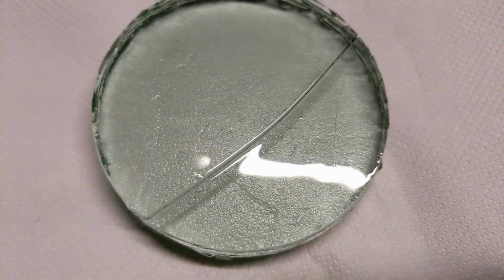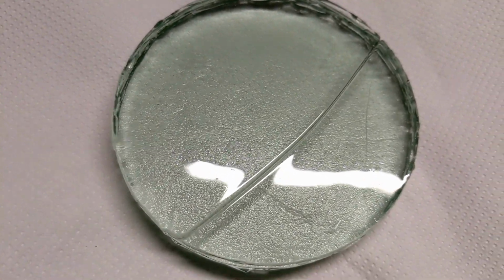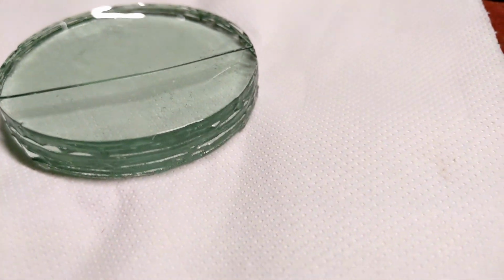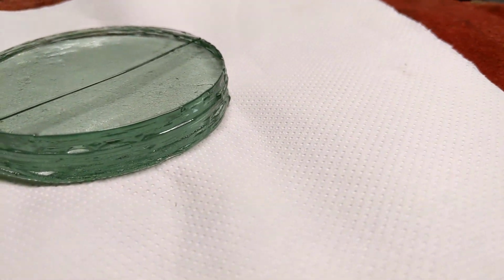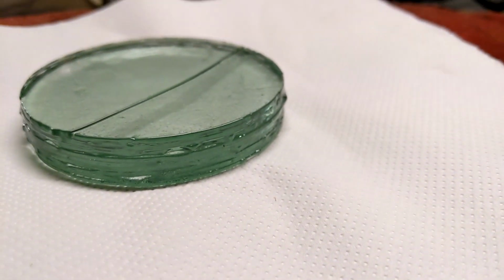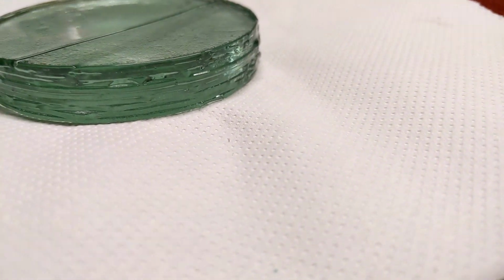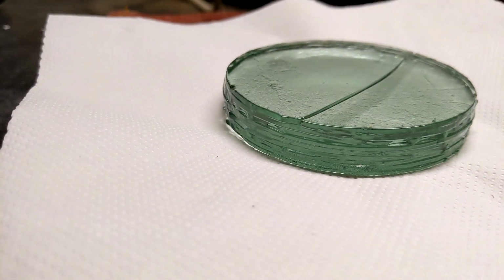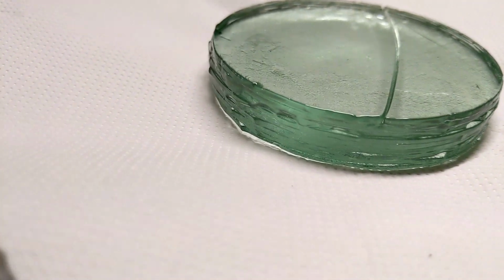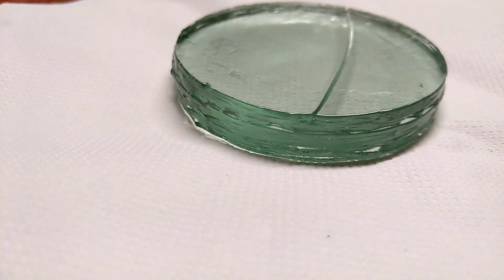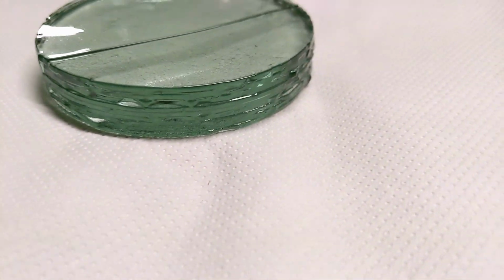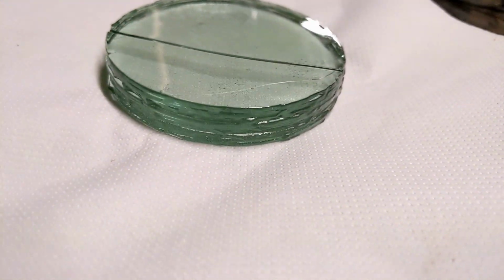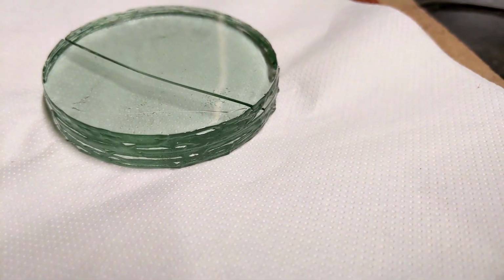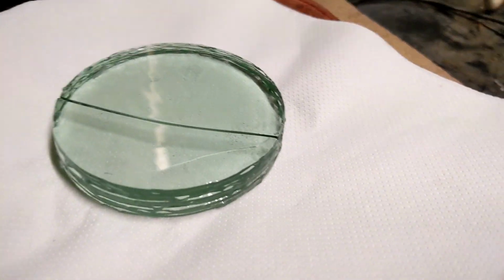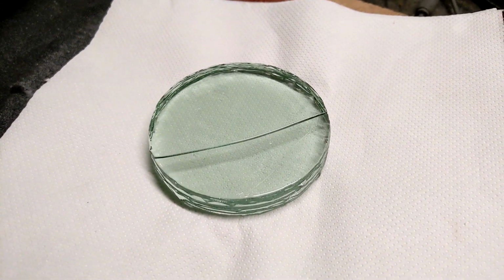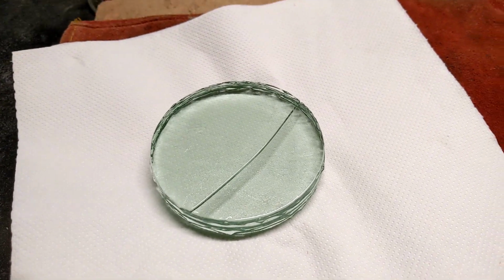So you can see the edges are rounded over, so it did sort of start to form together. The edges have fused to some extent. You can still see the laminations, but they mostly formed together. So that was with a top temperature of 775 Celsius, I think, which was the recommended tack fuse temperature, I think, for float glass.